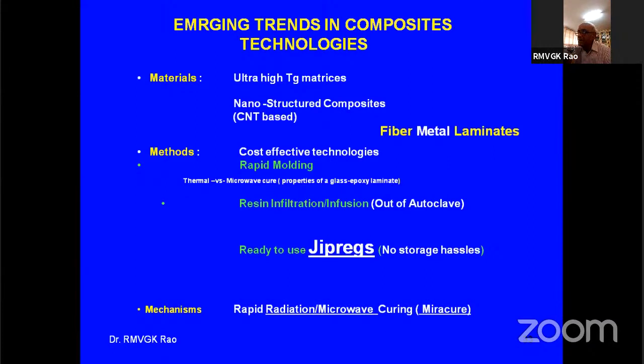But the important point is, if you make carbon nanotubes in that small powder form, they won't give us reinforcement. They have to be far lengthier, like crossing the critical fiber lengths. So if you can make carbon nanotubes into ropes and long fibers like glass fiber or carbon, you can make your aircraft or spacecraft a lot lighter. Because carbon nanotubes modulus is 1 terapascal, that is 1000 gigapascal. The best of carbon fibers today, lengthy fibers, range from 250 to 400, 500 modulus, or 600 at best, but they're very expensive, not accessible to everyone.